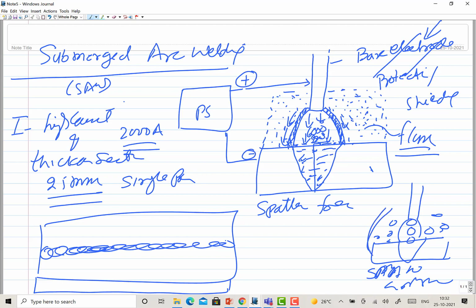But in case of submerged arc, since the arc is covered by the molten flux layer, there is no scope for spattering, and therefore whatever molten metal is being produced at the electrode tip is completely transferred. So spatter free weld is produced, number 1. Number 2, whatever heat is generated by the welding arc, everything is used because the arc is covered by the molten flux layer as well as the unmelted flux layer. So it doesn't allow the losses of the heat from the arc.